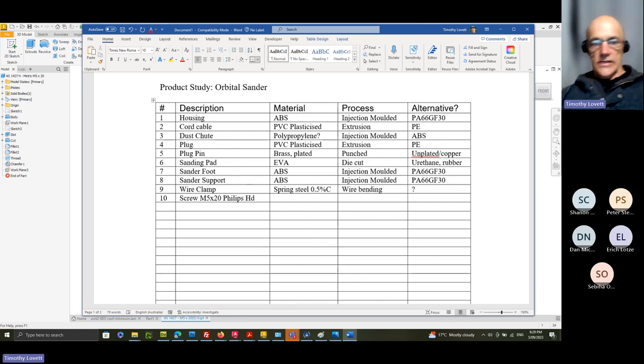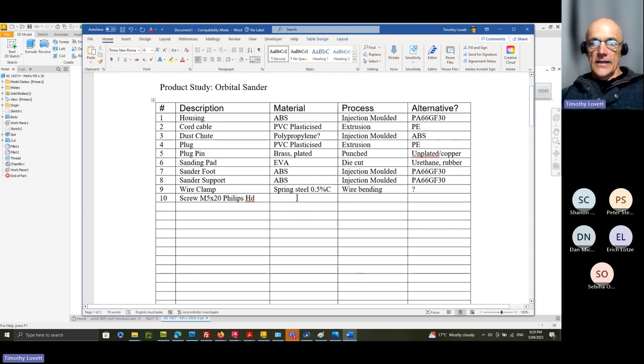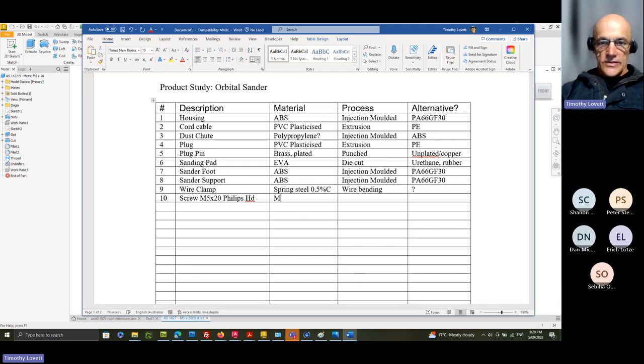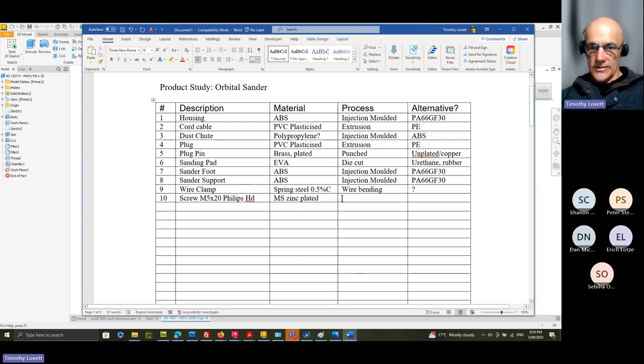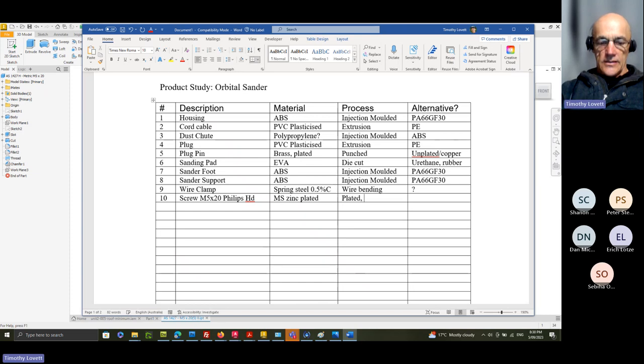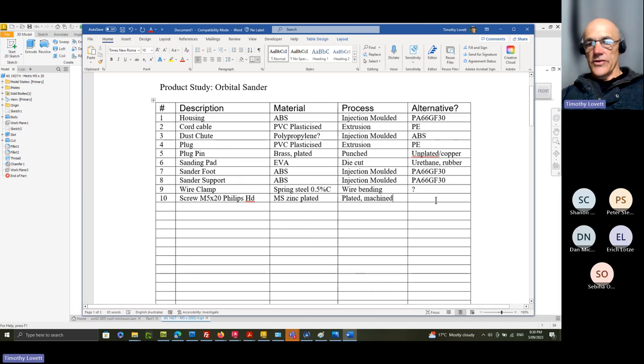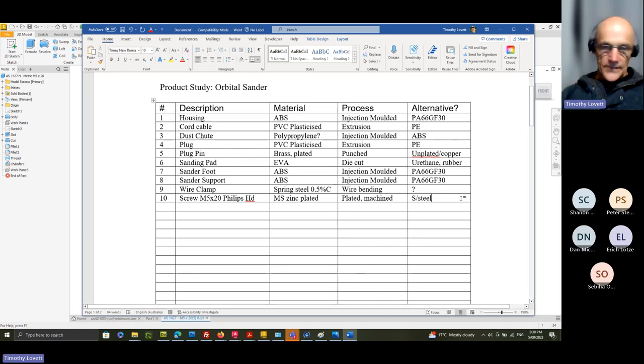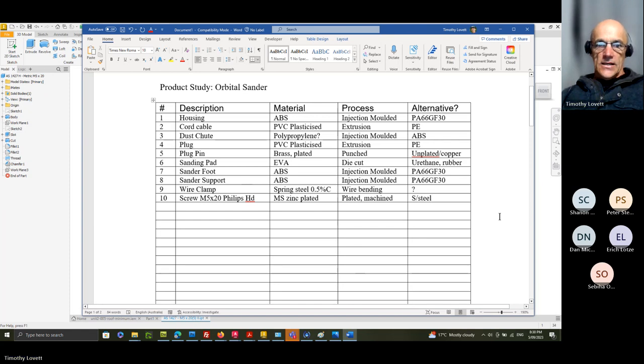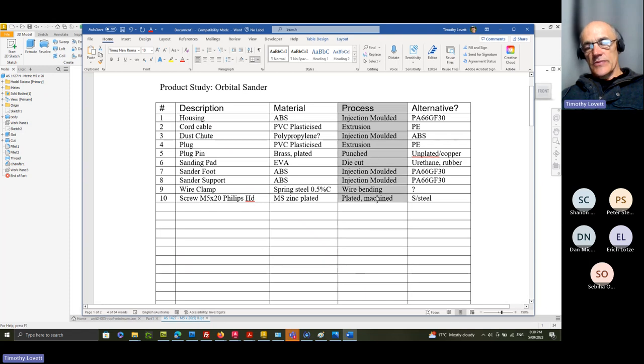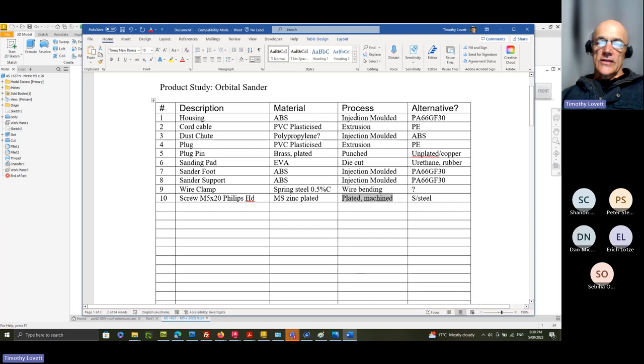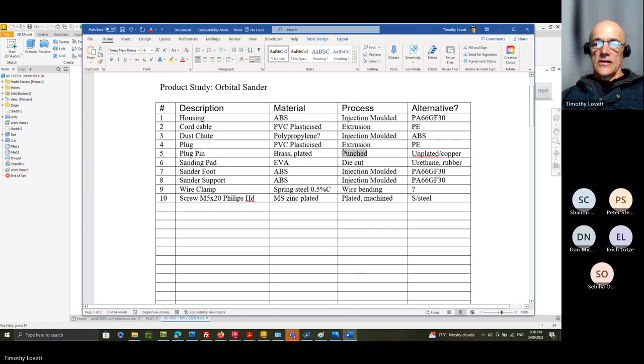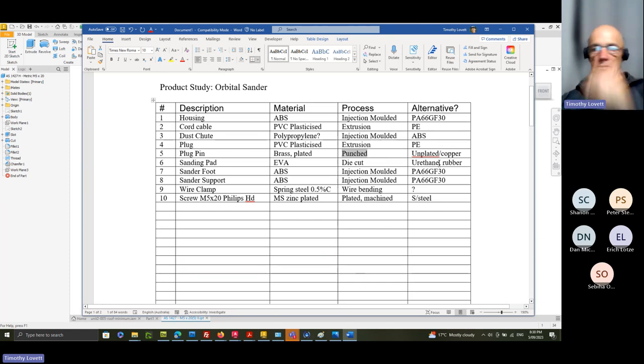So this bolt screw is a M5 by 20 and then it's a Phillips head, you can just shorten that. Material will be mild steel and zinc electroplated, not hot dipped, it's way too small. The process now, well it's plated and machined and pressed as well. Alternative materials yeah it could have been stainless steel that'd be nice but you're not going to find stainless steel screws on that cheapo sander. Do you get the idea? Just pay a bit more attention when it comes to screws and when you have plating and processes. In the process always put the last process first, you just say injection molding that's the last process. This one here punching out the brass plate was the last process.